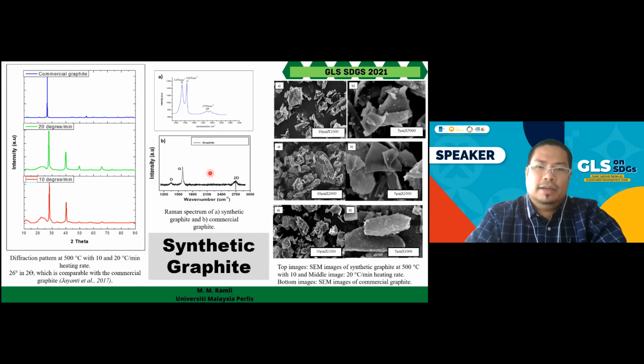Okay, again, if you look into the G peak, even though the ratio of D to G peak is very high, that is understandable because our graphite is a synthetic graphite. So the defect is quite high if you compare with the commercial one. But the G peak there, the graphitic peak, if you compare with the commercial graphite, is almost identical.